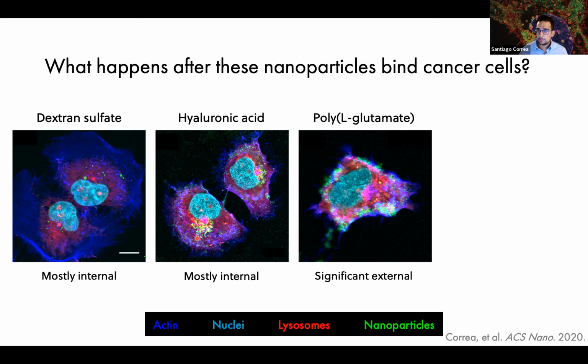So here I'm showing this poly-L-glutamate system. Recall that this is 24 hours after treatment with nanoparticles. And the main difference we see here is that this poly-L-glutamate-coated nanoparticle is being retained on the surface of these ovarian cancer cells rather than being internalized. This is a pretty surprising result. Since, as I mentioned before, normally when nanoparticles bind to the surface of the cell, they are generally internalized within